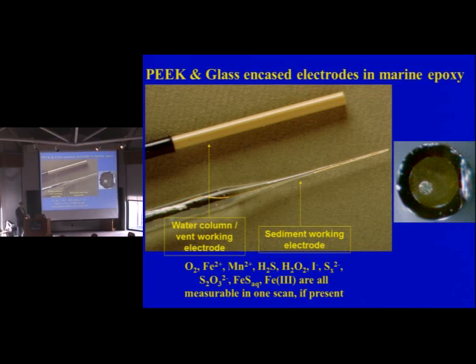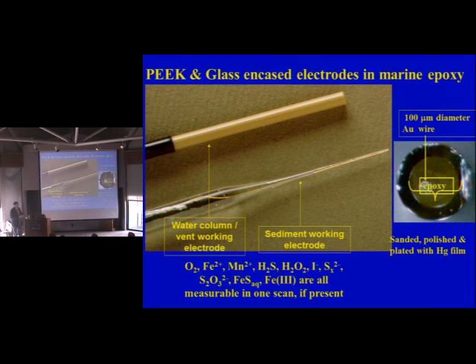The way the tip looks, this is one of our first ones. This is the 100 micron diameter gold wire. And you see the glass on the outside. And on the inside, we have a non-conductive epoxy from West Marine. And then what we do is we sand and polish this and it's almost optically flat. So we sand it with 4 different sandpapers from coarse to fine, and then 4 diamond polishes.